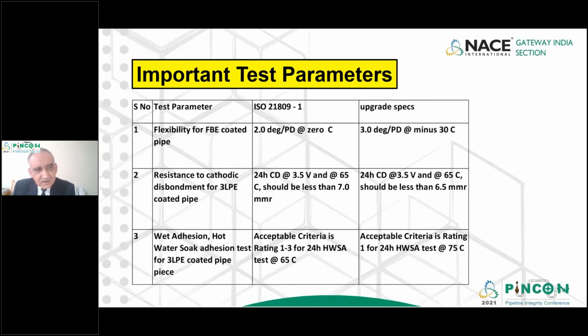The third parameter is hot water soak adhesion. It is actually a wet adhesion test, because when the pipeline is constructed and running, the soil could be wet. In many cases, the soil has a high water table and is very wet. So what is the continued adhesion level of the coating under these conditions? So there is a third test parameter which was created by this regulatory specification to simulate that service condition. So we generally test a 24-hour hot water soaking adhesion test at 65 degrees Celsius as per ISO. And what we have suggested to improve it, and many companies have taken the reference from CSA, is that the new requirement is rating 1 as per CSA, and the hot water soak adhesion test to be done at 75 degrees Celsius. This is the immersion test. So if they take care of these parameters, all others will fall in place.